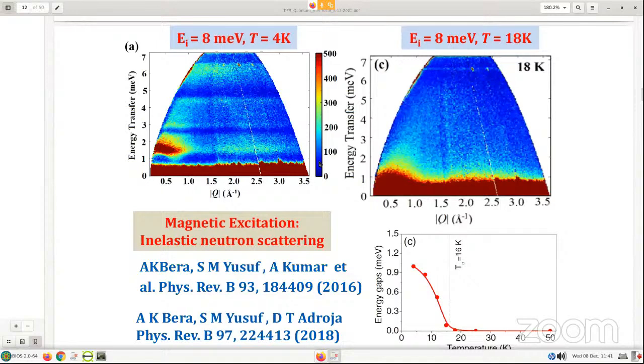Now we have also carried forward and done the inelastic neutron scattering. This was of course done at ISIS. The first experiment was done in BARC using Dhruva, but this experiment was done at ISIS. Here you see that at 18 Kelvin, which is above the Néel temperature, there is nothing, but below the magnetic ordering temperature, at 4K, you see the excitations. Without going into details, I will only say that there is an energy gap, and as a function of temperature this gap is increasing below this TN of 16 Kelvin.